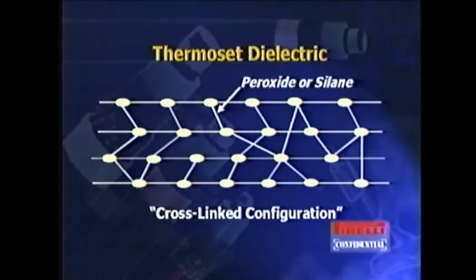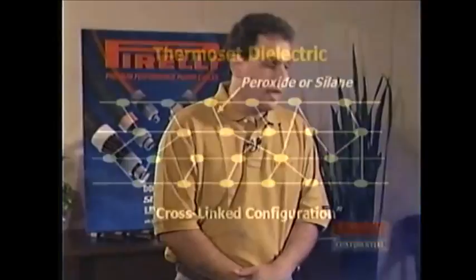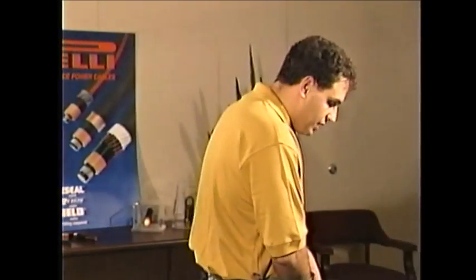In order to change a material from a thermoplastic state to a thermoset state, you have to introduce some cross-linking agent. There are various types of materials that you can use for that. One of the most common is peroxide, which is used very commonly in medium voltage cables. And peroxide is introduced, and you cure it under high heat and high pressure. And you have a cross-linking process, which in turn will give you a material that cannot be melted. Another way to cross-link a material is to introduce a compound called silane into the process. And you cure this using moisture. This is used commonly in low voltage materials and achieves the same effect.